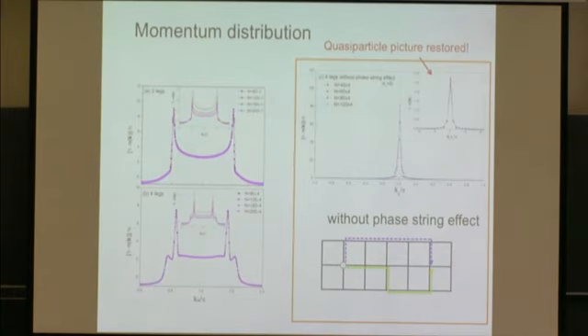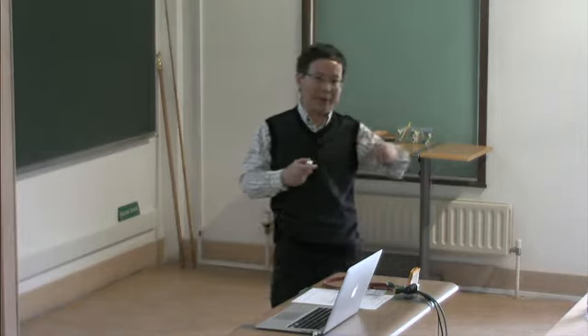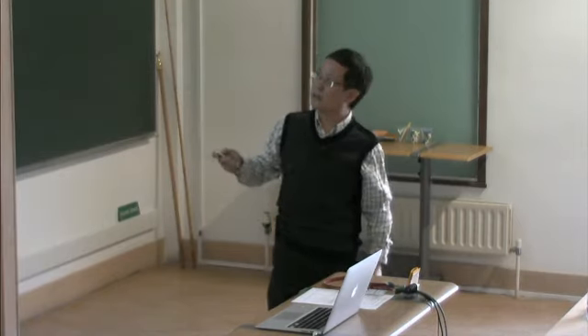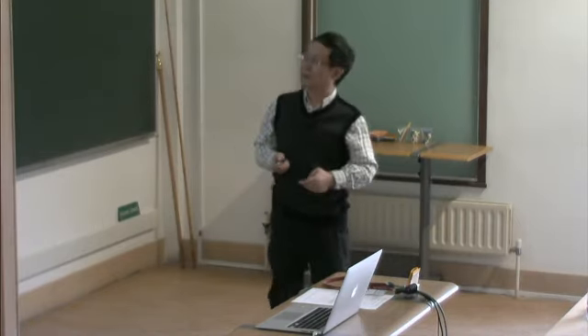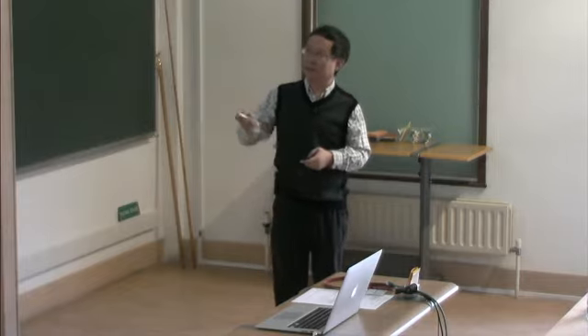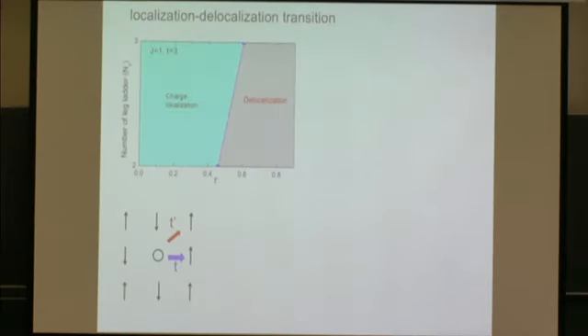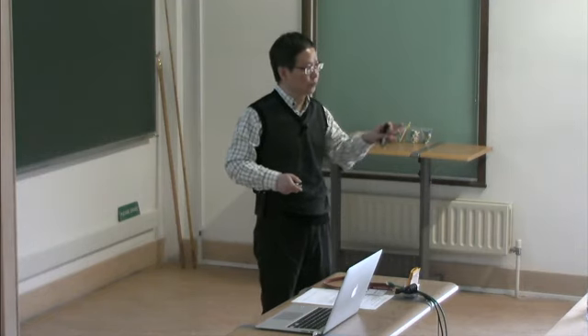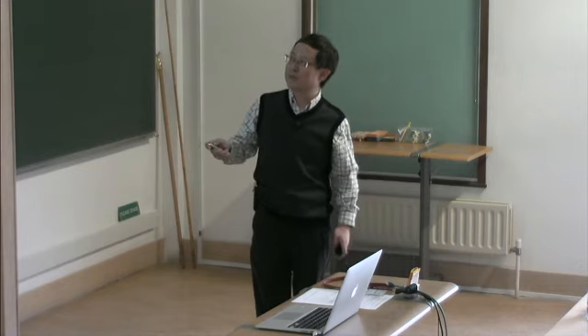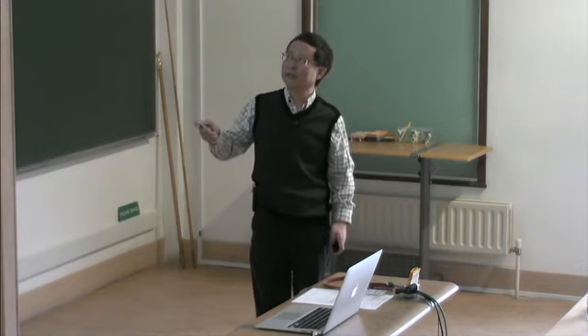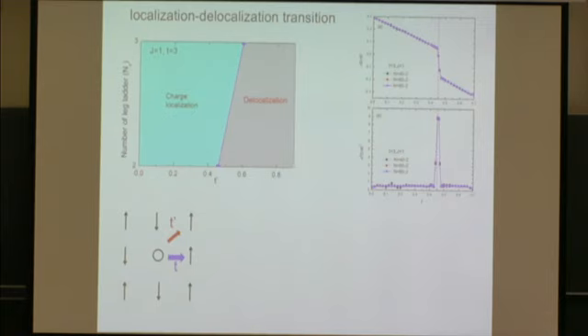So in other words, this hole will strongly interact with the background, such that the momentum will actually spread out. This is the localization feature. As mentioned, this sign structure only works for a bipartite lattice. If you add a next-nearest-neighbor hopping, the sign structure will start to be disordered. So you expect that when t prime is large enough, eventually the hole will become delocalized.